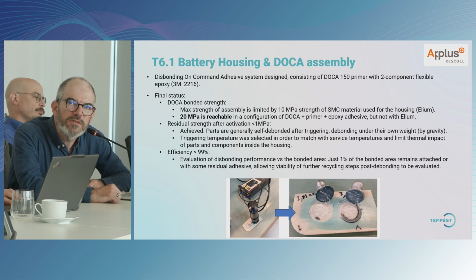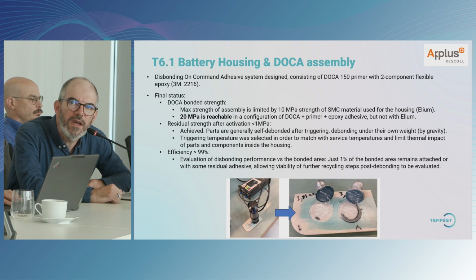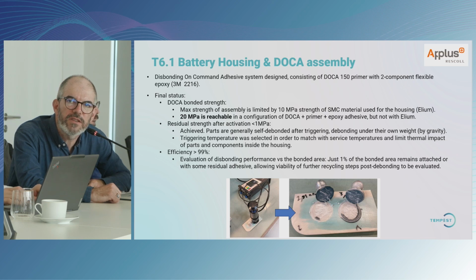The final status of all the work we've done within that project for this DOCA system was that we had a limit of the maximum strength of the assembly due to the SMC material, because we easily reached the failure within the substrate, within the composite. But in the end, with this system, we know that for etched metal, for instance, we can easily reach up to 20 MPa, which gives you an idea of the potential of the technology for this DOCA primer plus epoxy adhesive.